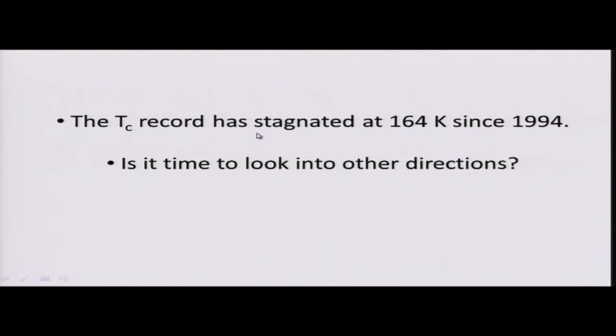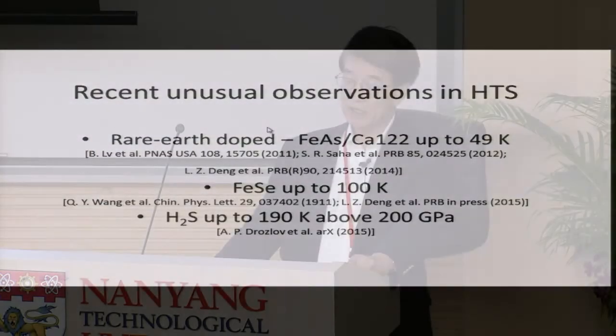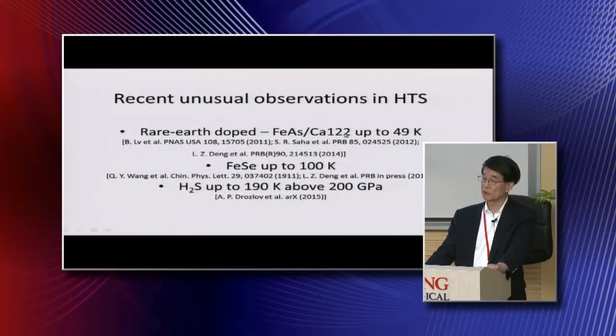So the TC record, unfortunately, has stagnated at 164 degrees Kelvin since 1994. Is it time for us to look into a new direction? So recently, there were three unusual observations. One happens in the iron-based material. This material was not supposed to be superconducting, but when you dope it with a little bit of rare earth, you can get TC up to 49. It's not a big deal, but then it's in single crystal, and therefore the superconductivity is non-bulk in a single crystal.